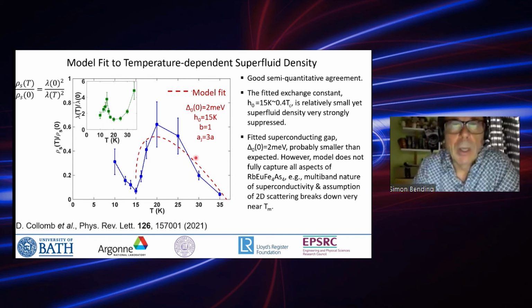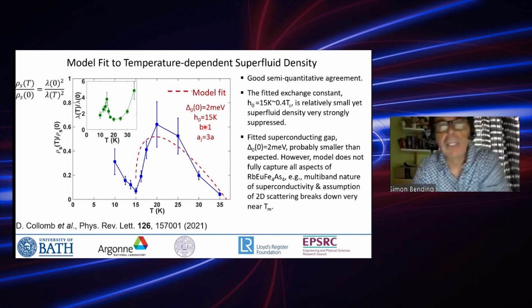The best value of the model fit, which admittedly is only semi-quantitative, is given by this dashed red line here, and the fit parameters here are for a zero temperature energy gap of 2 millielectron volts, an exchange temperature of 15 Kelvin, the spin correlation length given for B equal 1, and a non-locality of 3 europium interatomic spacings. So I hope you agree with me that the semi-quantitative agreement is good.